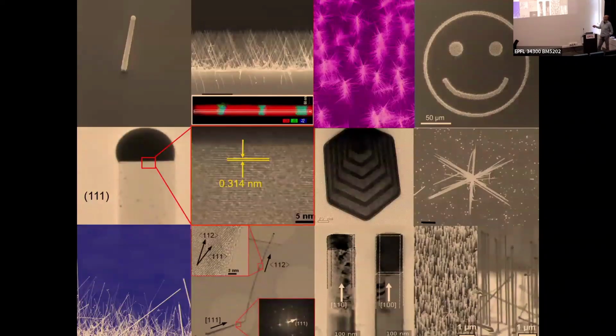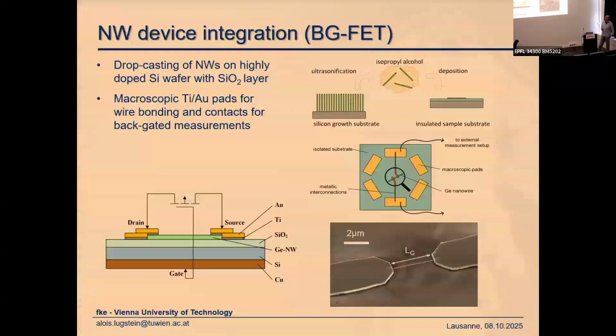So we have a freestanding germanium nanowire. This is a carpet-like growth of silicon nanowires. We've grown heterostructures, intentionally kinked nanowires, and so on. To make devices thereof, you have to integrate them in the device architecture, and therefore we harvest the nanowires by ultrasonification in isopropyl alcohol, and then we deposit the nanowires on an oxidized wafer, and we make electrical contacts by e-beam lithography, sputter deposition, and lift-off techniques.